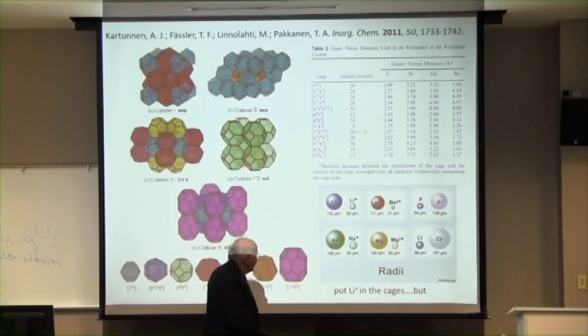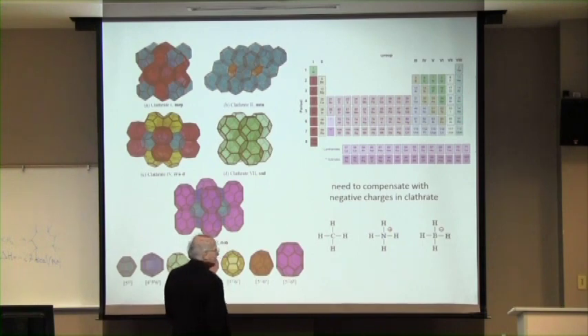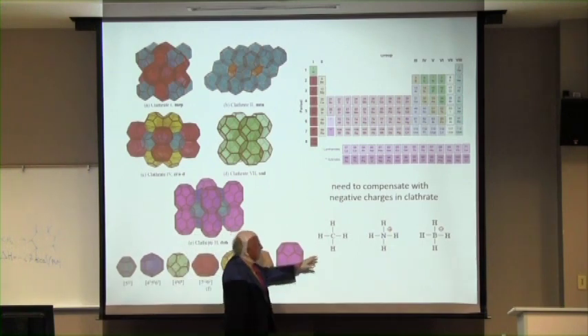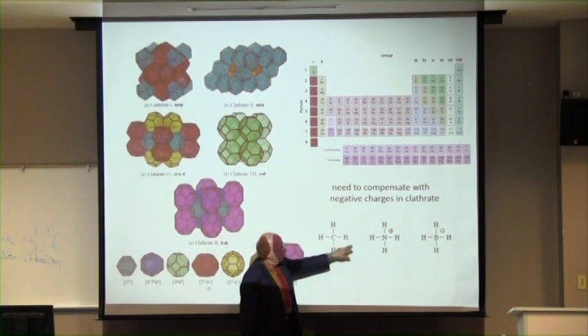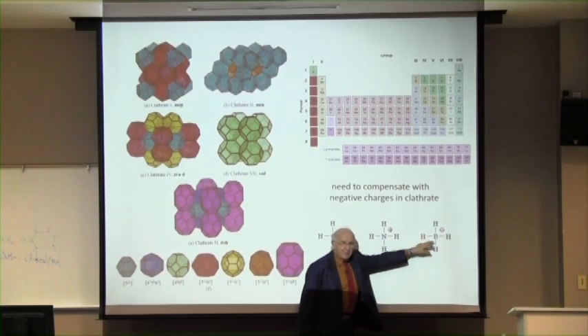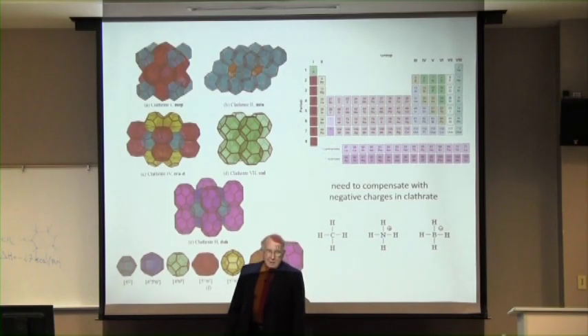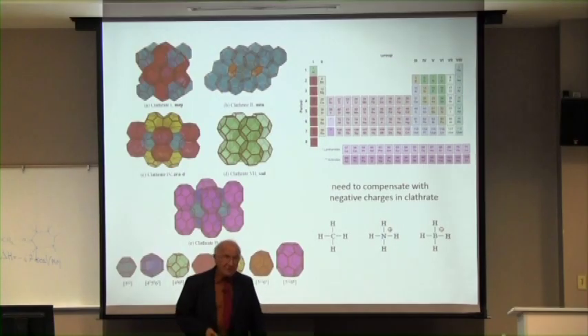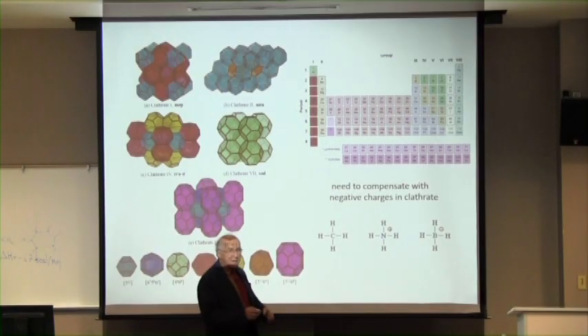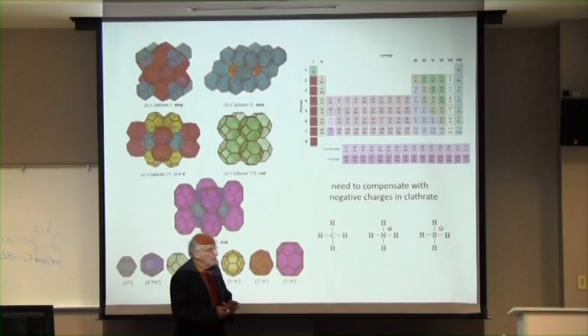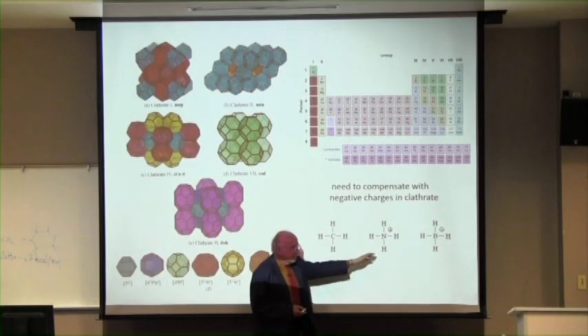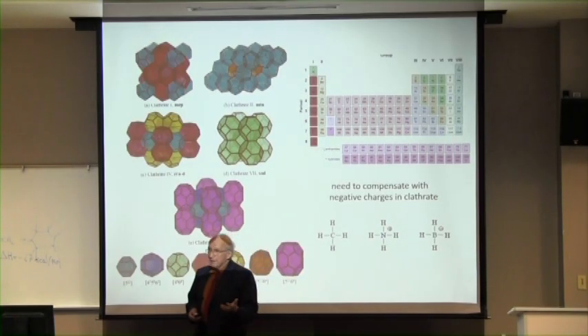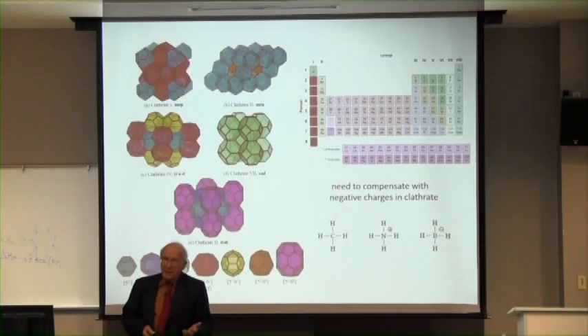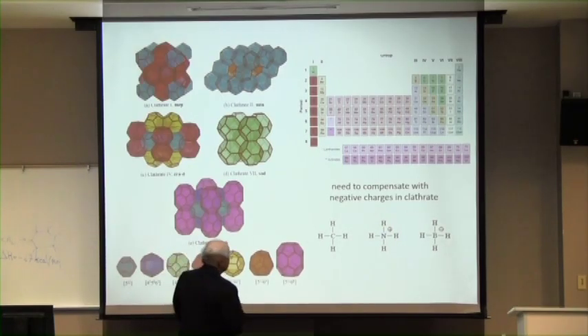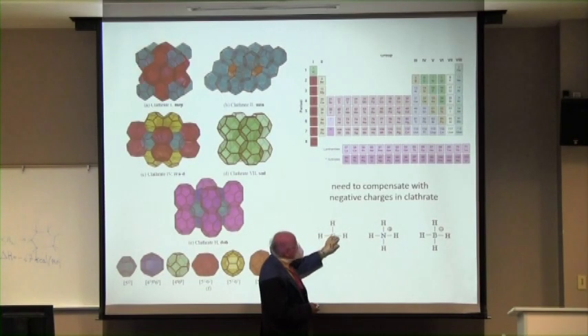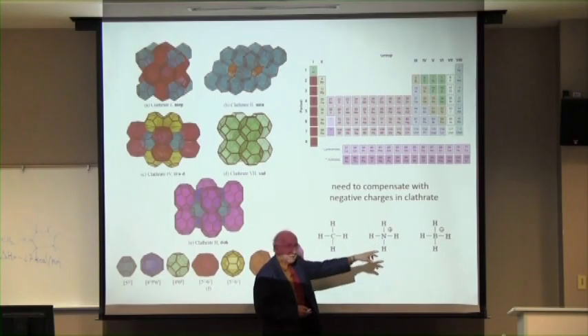So what we did was the obvious thing a chemist would do, and that is, take this carbon and replace a few carbons by borons. Because the size of a boron is not that different from that of a carbon. These are isoelectronic molecules: ammonium, methane, and borohydride. Every time you take a C and put a B in it, and make it form 4 bonds, it's got to be a B minus.